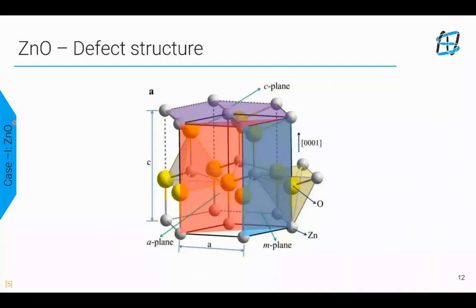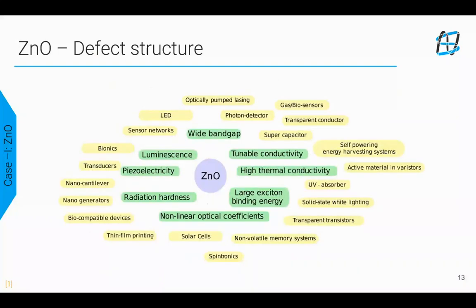Now the crystal structure here, zinc oxide, is a wurtzite-based structure. So it has a 6mm point group symmetry. And as you can see here, there is this m mirror plane and there is this a mirror plane. And then the polarization is along the c axis. Here they're showing you the c plane, which is a polar plane, but the polarization is along this axis. And since this crystal is non-centrosymmetric, it is polar, it exhibits spontaneous polarization. ZnO is reported to have good piezoelectric properties and also optical properties. So yeah, let's look at the properties that this kind of symmetry would bring up.